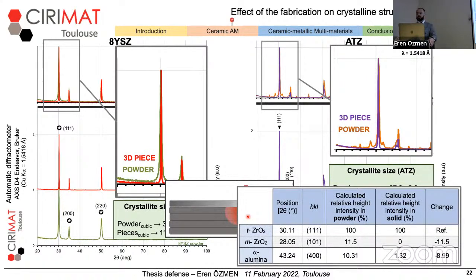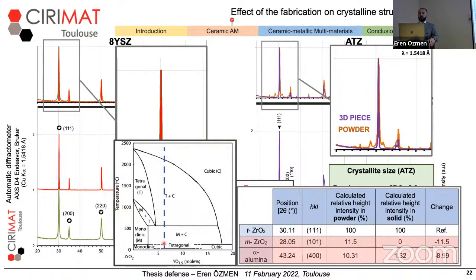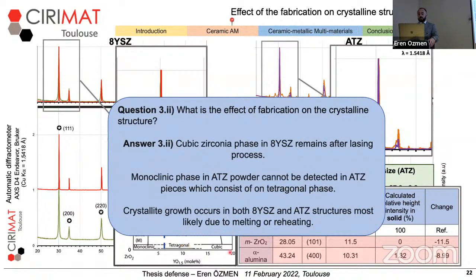So when we calculated the relative intensity of phases in the ATZ pattern, we see that the monoclinic phase completely disappears from the structure. One explanation for this can be found in the phase diagram between zirconia and yttria. The composition might be going to complete melting, and during cooling down, due to fast cooling or quenching, the composition might be stable in the metastable tetragonal phase. And we can answer the second part of the third question here. Crystallite growth is observed for both materials, and while fabrication is not causing phase change in 8YSZ, fabrication caused the disappearing of the monoclinic phase in the ATZ structure.